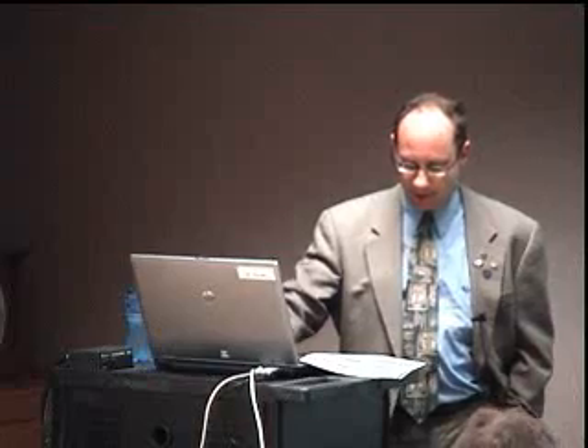One of the things that contributes to the ugliness, shall we say, of some of these cracks is if you have any rust stains coming out of them. And in some cases, it looked like what had happened is you had cracks at the vandal protection fence base plates where you then had a little bit of corrosion and material coming out of that. If you're using epoxy-coated rebar, I wouldn't think you'd see too much evidence of corrosion coming out. In some cases, we really didn't see any particular staining.